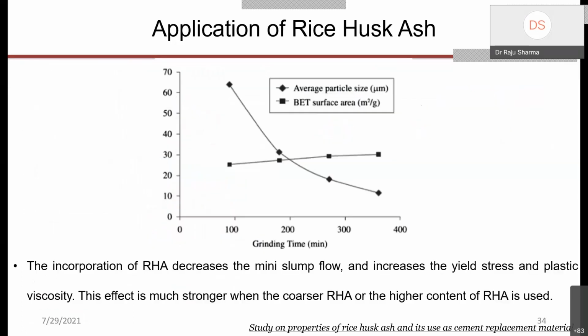Fine. So now if you see the fineness in terms of surface area, when you increase the grinding time, your average particle size is going to decrease, right? And your BET surface area is going to increase. And by that you can justify your workability results. If you fix the content of your liquid, your workability may decrease, because the finer area increases and then they need more water. So accordingly, you have to change the water content.